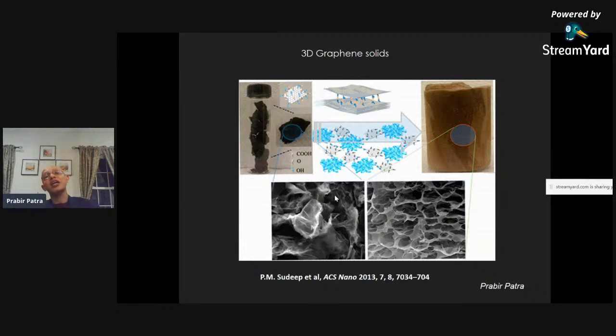Then we thought, can we make 3D structures of these? So here we made very nice fabrications using mechanical engineering and some aspects of chemistry, and then we formed a 3D graphene oxide solid. And if you look at later, graphene oxide was reduced into graphene. Now we form very nice conductive porous scaffolds as if they are stacked. Now inside those scaffolds, I can put some brain organoids. Like we can grow some brain cells, and on both sides we can put contacts and connect to the computer device. And you can see how brain markers are sending signals all across. Then map those signals and understand what is happening in the brain.